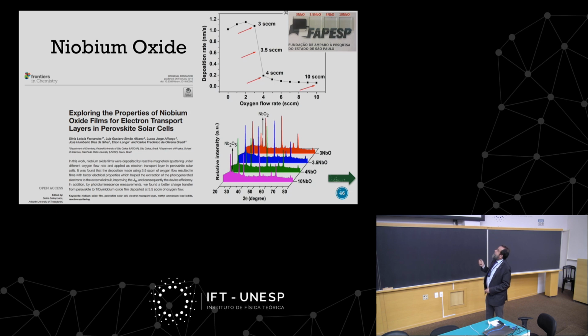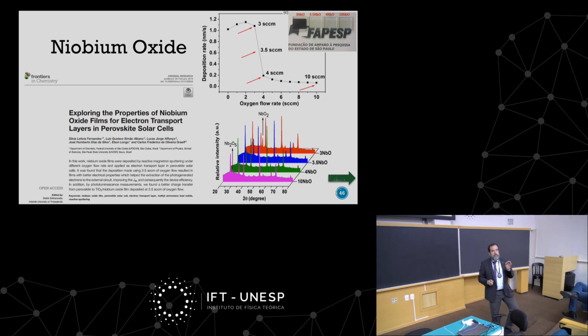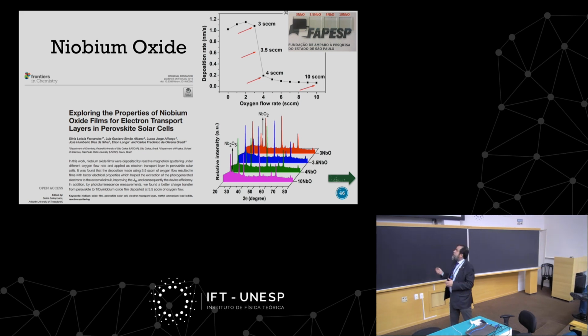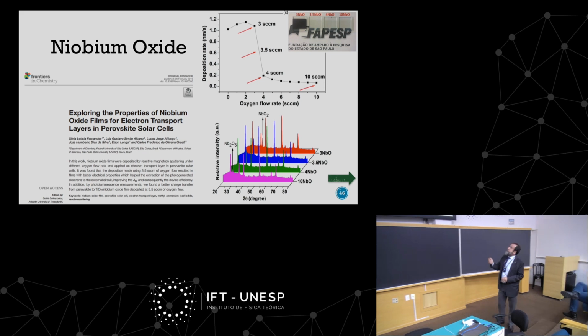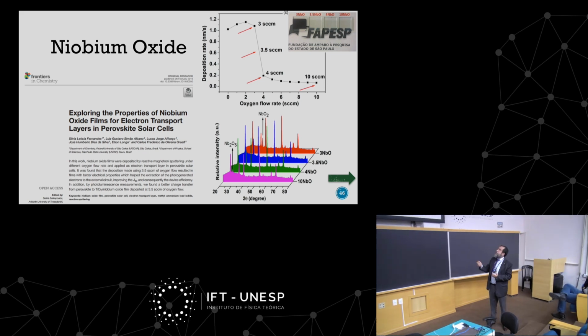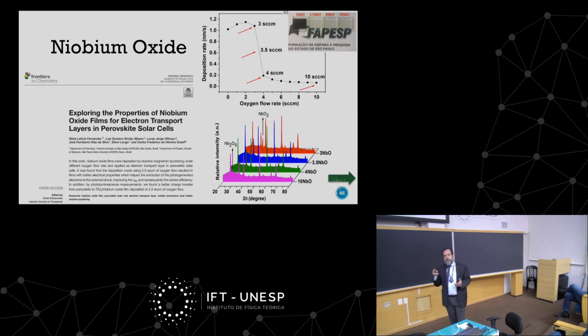The only thing that I want to go into a little bit more detail is exploring a little bit the composition of the niobium oxide. One nice thing about working with ceramics is that you can dope, you can change the electrical properties just by changing the composition. So that's what we did. We changed the amount of oxygen inside the chamber during the reaction. Okay? And as you can see, you can have dramatic change that you can see with your eyes. So if I put too little amount of oxygen, 3 SCCM, the material becomes black because I'm not producing any more niobium pentoxide, but niobium dioxide, NbO2.